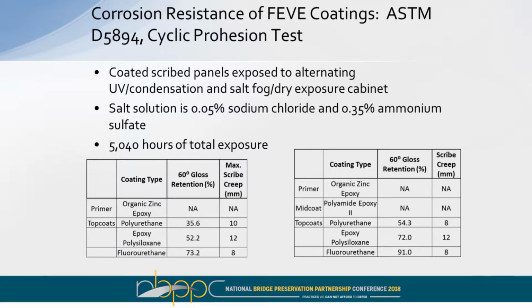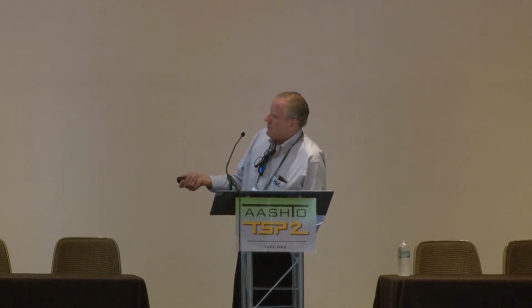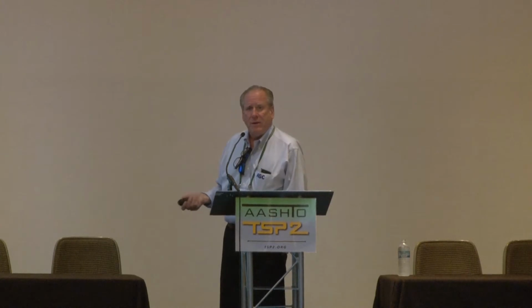This is a cyclic Prohesion test, and basically what you're really looking at over here is the maximum creep, and I think there's an AASHTO standard that requires an 8 millimeter maximum creep, and you can see the fluorourethane does have good maximum creep and good corrosion resistance. The real differences come when you're looking at the gloss retention over a period of time.